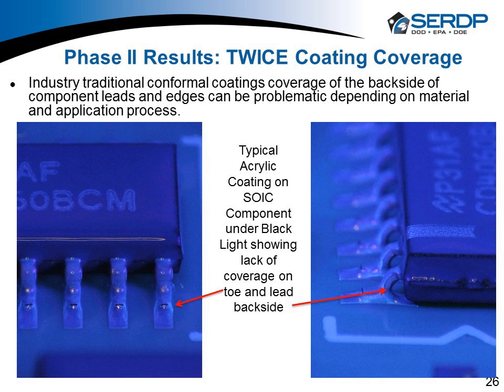One of the big questions that was asked during the program was, okay, coatings look great, but we know from conventional coatings out in the industry, there's concerns about coverage. And this is a picture here of an acrylic coating on our test boards, and you can see that the very sharp edge of the toe does not retain coating, or the back side of the lead here on the picture on the right on slide 26. You can see where under black light, we have good coating out here on the solder joint and the face of the lead off the SOIC, but the back side gets shadowed, and just standard conventional coatings without taking account into that leave a problem.